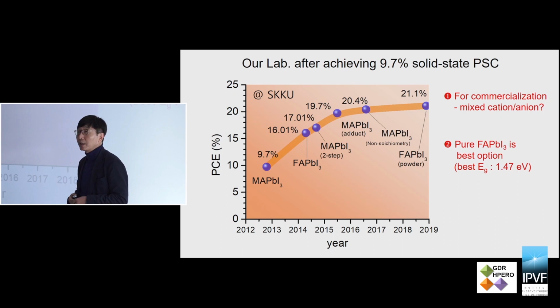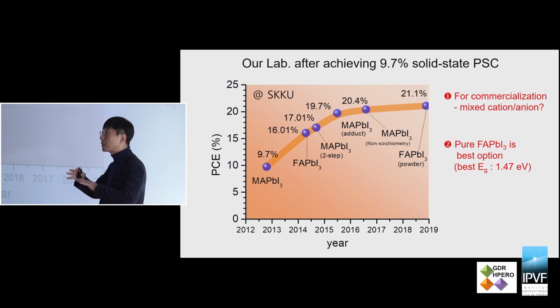And in our lab, actually, we focused on the pure MAPbI3. The 25.2% efficiency is based on a mixed cation, mixed anion composition. But I was curious whether such a mixed composition may undergo phase segregation, and also probably it's not suitable for commercialization because it's difficult to handle such minor compositions. So we focused on the pure MAPbI3 or FAPbI3.